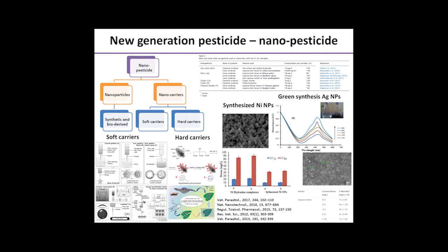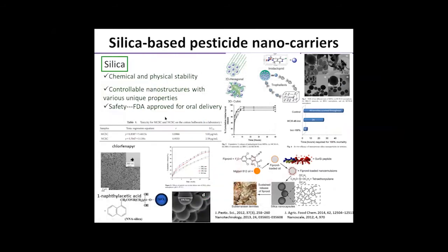Soft carriers such as polymers and lipid nanoparticles, and hard carriers such as nanoporous silica nanoparticles, have all been reported to be used for the encapsulation of pesticide actives. Among these carriers, nanoporous silica nanoparticles have unique properties, including high porosity. The high porosity is beneficial for loading the active as the payload. They also have a stable rigid framework, ease of synthesis, and excellent biocompatibility, which are ideal parameters for agriculture applications.